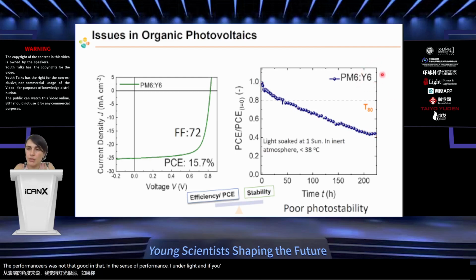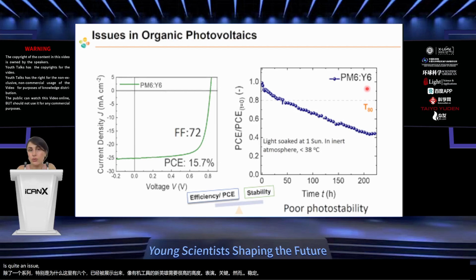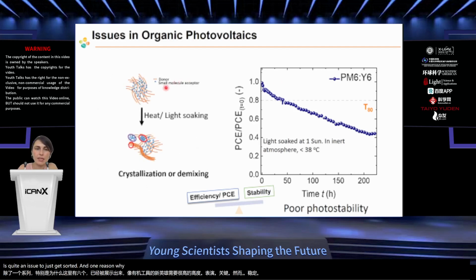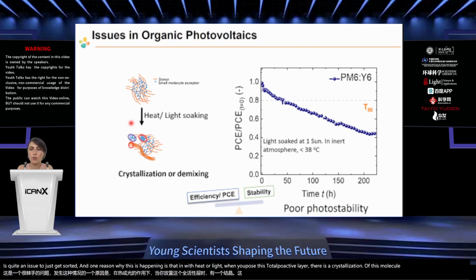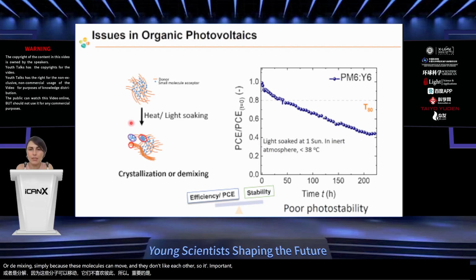If you're familiar with the field, that's why the Y acceptor series, and specifically Y6 here, has been shown as the new hero for organic photovoltaics, and quite high performances were achieved. However, the stability is quite an issue to get sorted. One reason why this is happening is that with heat or light, when you expose the photoactive layer, there's crystallization of these molecules, or demixing, simply because these molecules can move and they don't like each other. So it's important to find material systems that like each other, or find techniques that would lock your morphology along with the proper interfaces for stable solar cells.